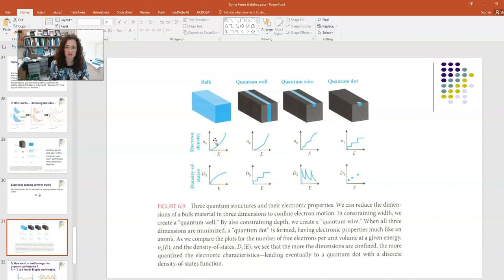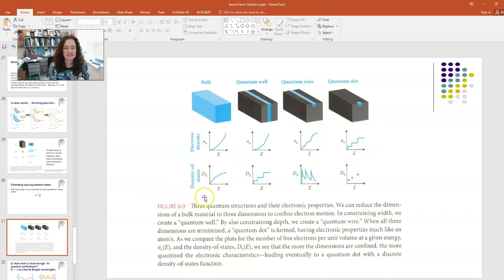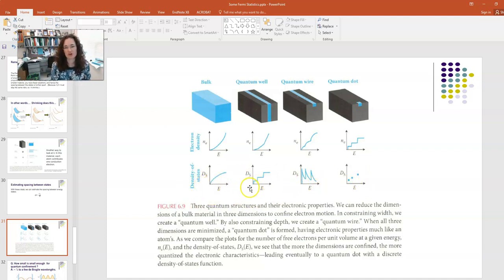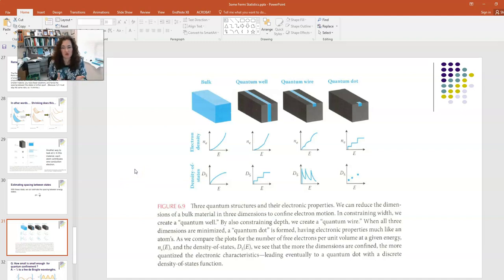The electron density function changes as you confine in more dimensions — as you can see going across the top — and it looks more and more like a step function. The density of states also changes. For a bulk solid, the density of states is proportional to the square root of energy, pictured in the leftmost graph. As you confine, it looks more and more strange and quantum — going from a smooth function to step functions, to jagged peaks, to just dots — representing the quantum structures and their electronic properties. As you reduce dimensions further, you wind up at the quantum dot, which mimics what's going on in a single atom. This is what we call quantum confinement.